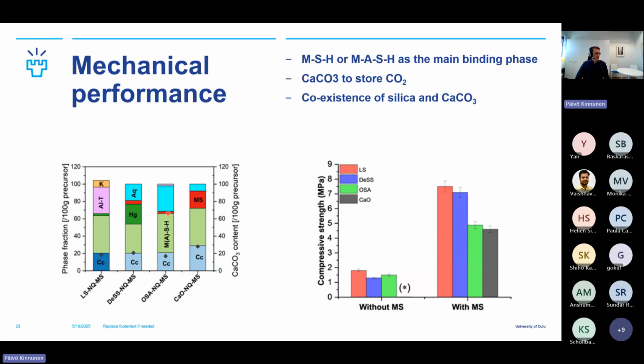Microsilica. So for some, we added microsilica in order to see what would happen to the calcium carbonate. And it turns out that yes, we can have coexisting calcium carbonate and MSH or MASH, and we can actually also get decent compressive strength. This is about 5 to 8 megapascals, and these are not, of course, optimized.